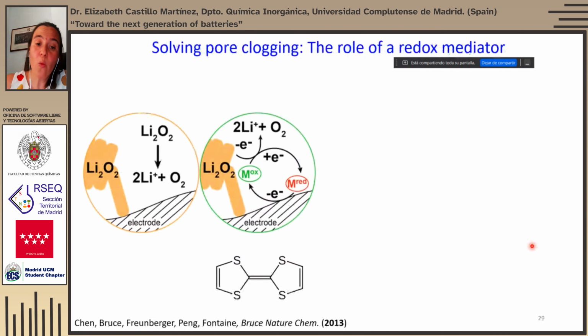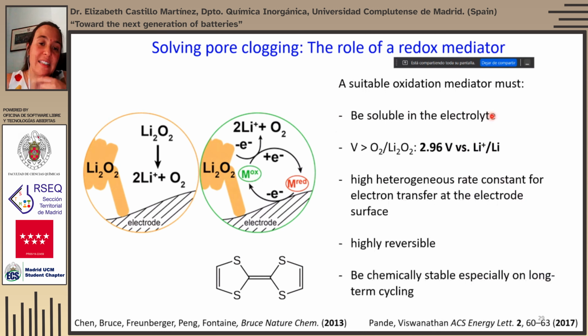So in this sense, the main strategy has been to use redox mediators, which are soluble in the electrolyte, and instead of reacting with the lithium peroxide particles in the region where they are in contact with the electrode, they react with the bulk of the lithium peroxide in solution. And this proves to be a very big improvement in reversibly reacting this battery chemistry. So it is important that the redox mediator is soluble in the electrolyte, that it has an oxidation potential above the oxidation potential of the lithium peroxide that we want to oxidize, and of course that this reaction is fast enough.